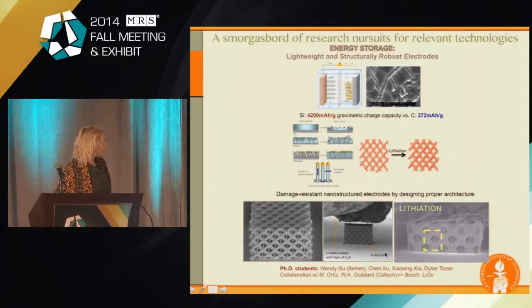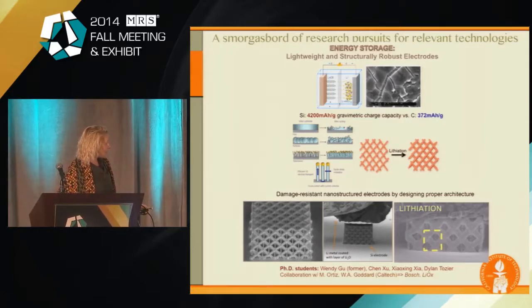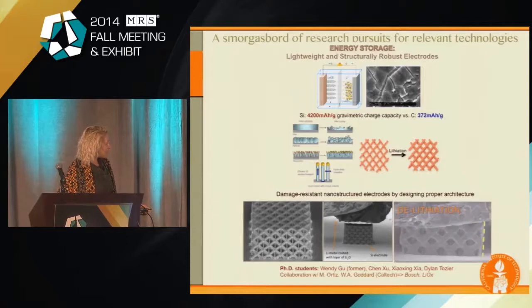I'm showing you this yellow one as an example. Do you see it lithiating? Do you see it magnifying and blowing up? Right, so it blew up quite a bit, but I don't see any catastrophic cracks here. And then this is the delithiation, so you could see it shrinking. So they figured out a way to lithiate and delithiate these structures without any kind of failure.